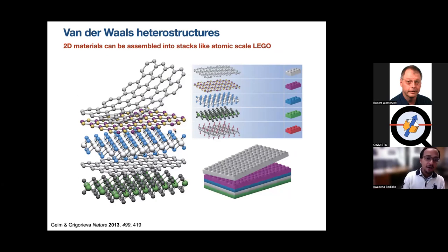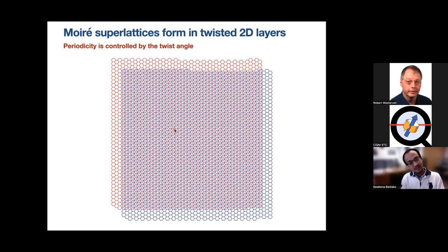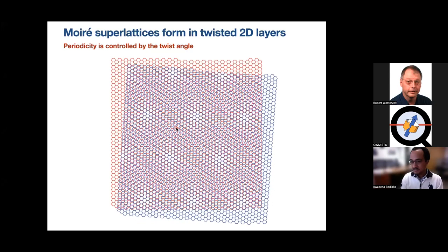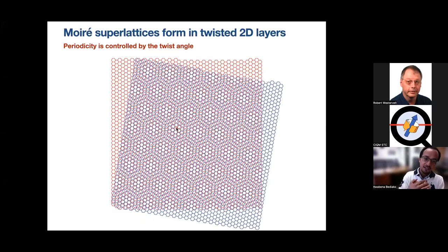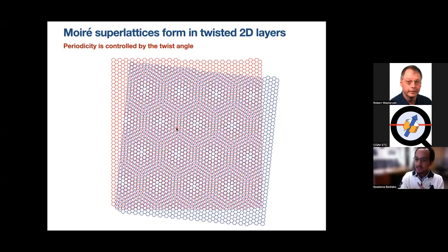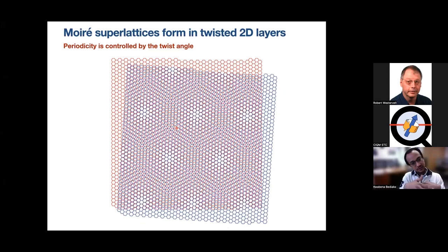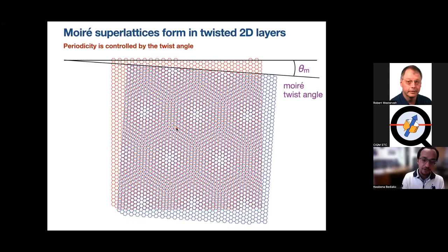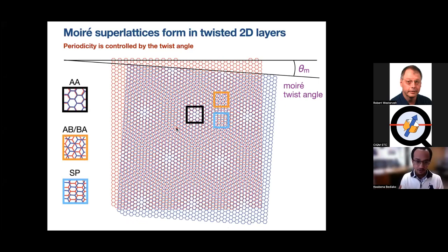Okay, great. Now, what I'm going to talk to you about is another degree of freedom that is possible with these systems, where unlike Legos, where the blocks lock into place and my kids love to play with them, here, when you take two layers of a 2D material, as many of you know, it turns out that you can actually control the interlayer azimuthal misorientation between the layers, so the interlayer twist angle, and this gives rise to a longer range periodicity called the moiré superlattice, with a periodicity that is determined by the twist angle.